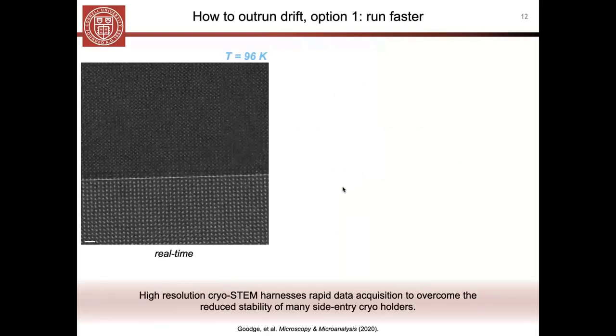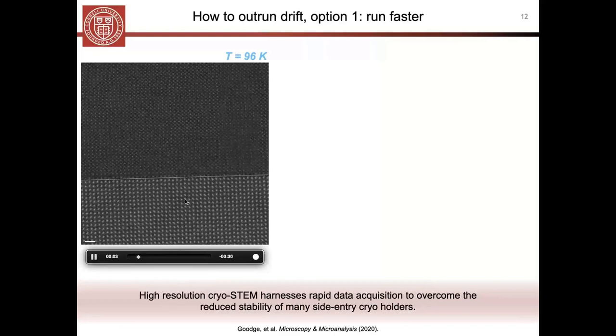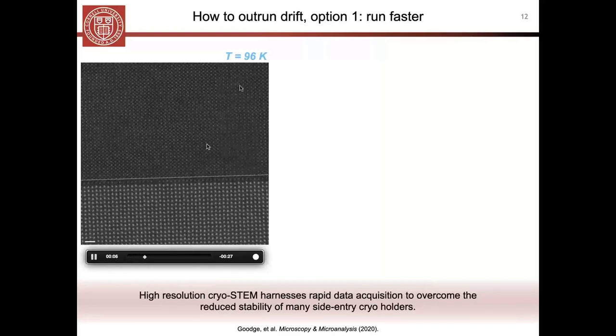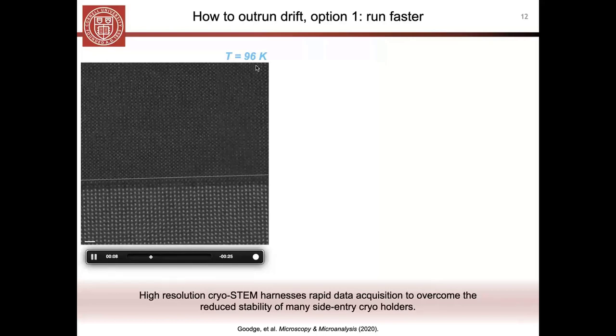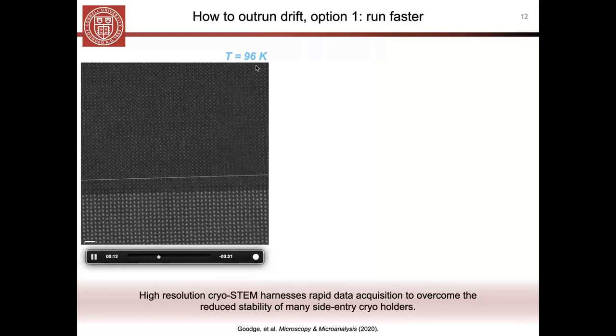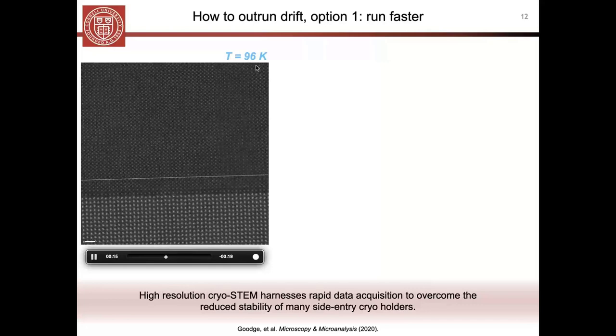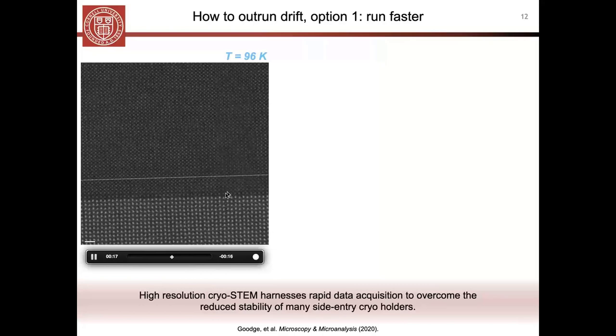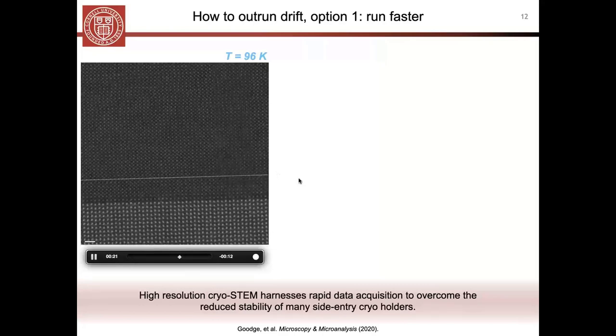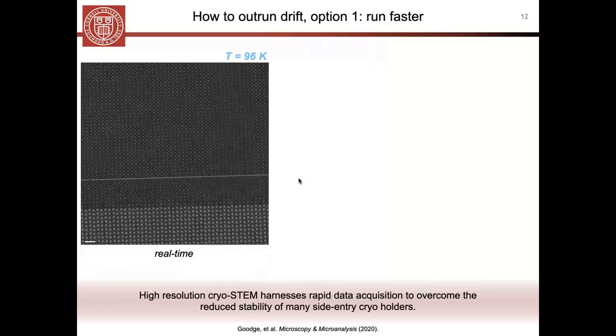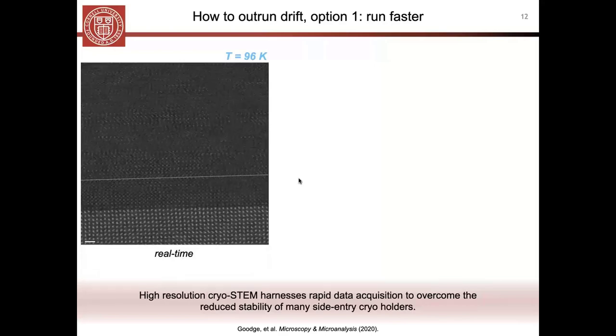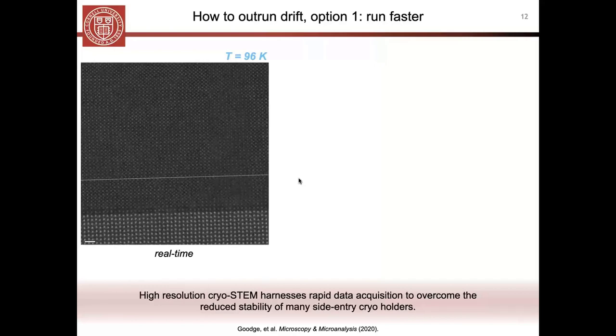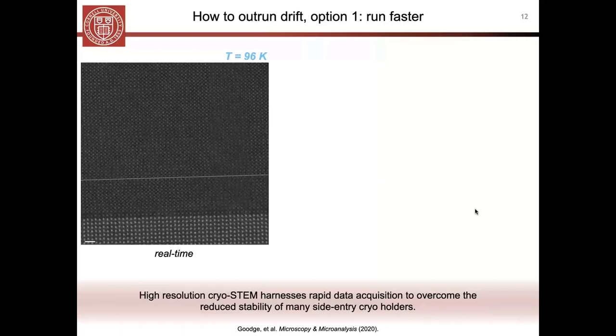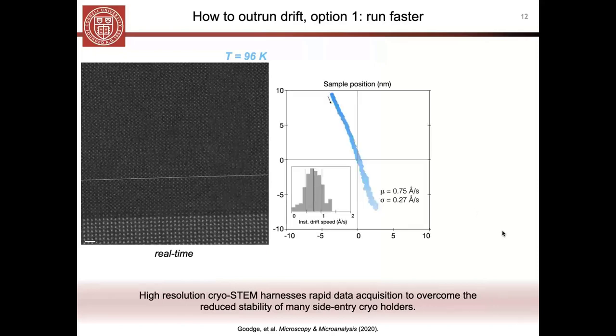And so what does that look like? Well, if you take a STEM image of this interface under liquid nitrogen cooling, with this movie played back in real time, you can see how quickly that interface, which is basically just a place marker, drifts away from where it started. You can imagine that if that's the feature you're interested in studying, it relatively quickly moves away from the original field of view. And in that last frame you just saw maybe a bubble in the cryogen or something even more disruptive. But this large-scale thermal drift is what really limits especially slower acquisitions like EELS.